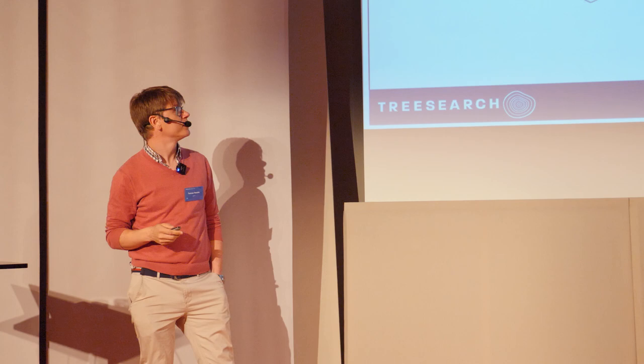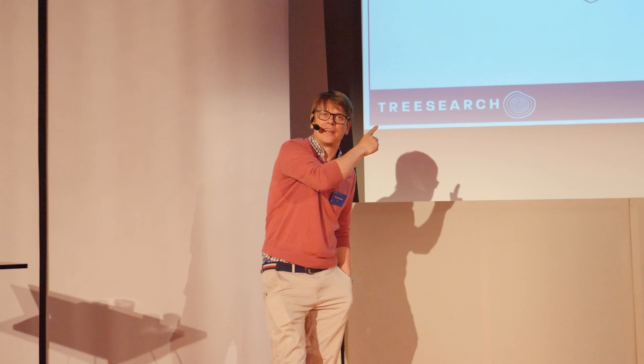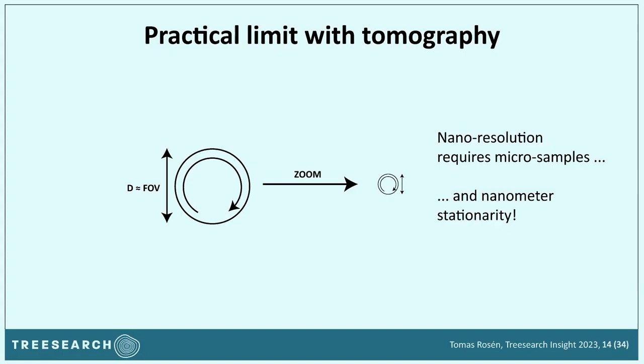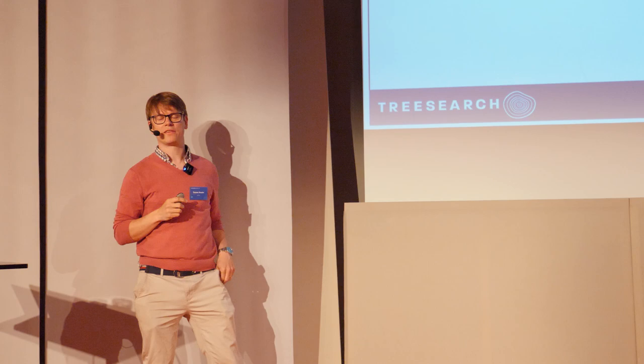This is especially a problem on the nanoscale, where things tend not to be completely stationary — mainly due to Brownian motion, with molecules hitting your sample from all directions. Another practical challenge with nanometer resolution in tomography is that your sample needs to be on the order of micrometers in size, which is very hard to handle — if your sample needs to be thinner than your hair, it's very difficult to place on the rotation stage.